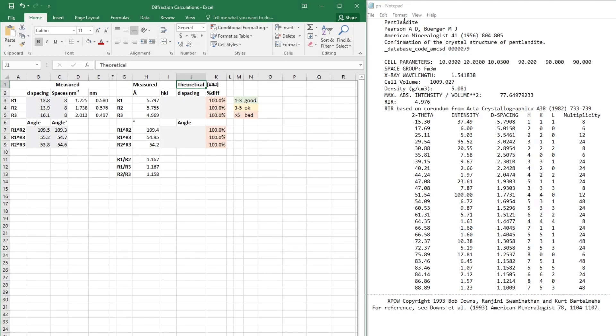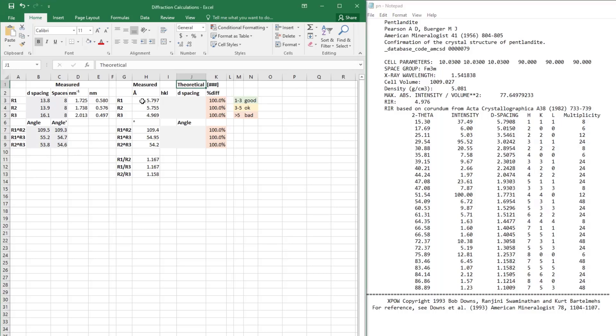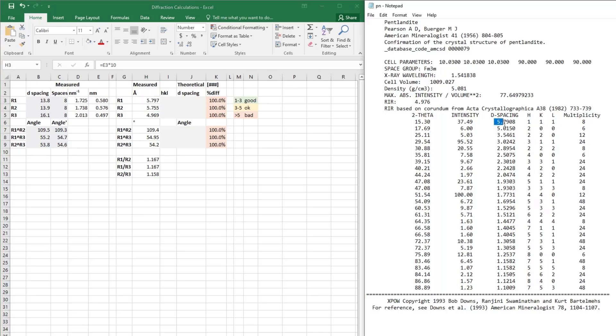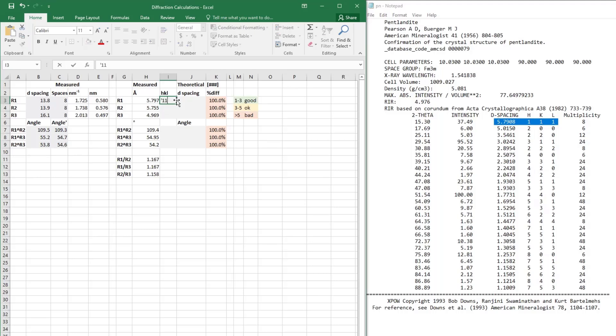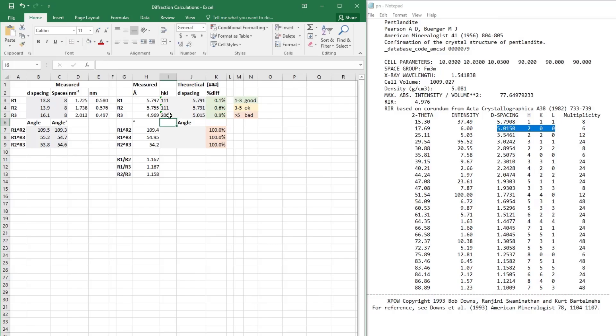Now we're going to compare the literature data to our measured data. This is the diffraction file that I got from American Mineralogist database. It gives the D-spacing and the HKL of the planes. I want to see what the closest values are to my measured values. I have 5.79, and I get a good match for that on the 1-1-1 plane. This has a multiplicity of 8, meaning there are 8 symmetric spots that have the same D-spacings. You can assign R1, R2, R3 the same planes if those do exist by symmetry. R1 and R2 both matched 1-1-1, and then R3 best matches 2-0-0.